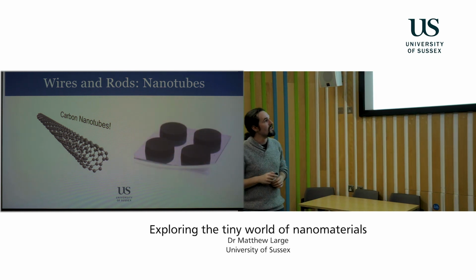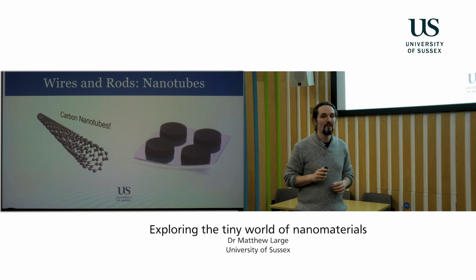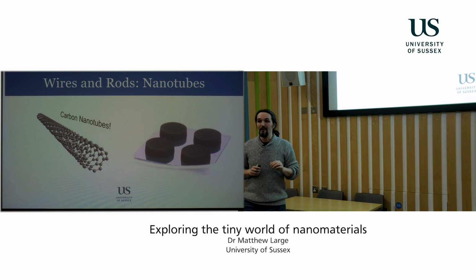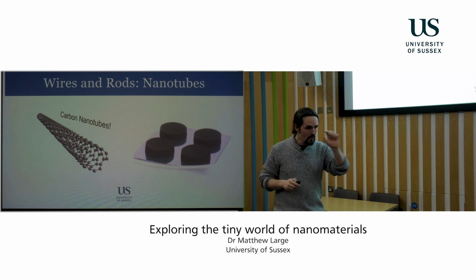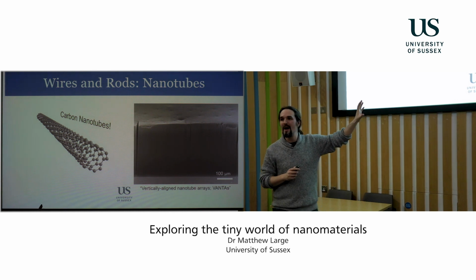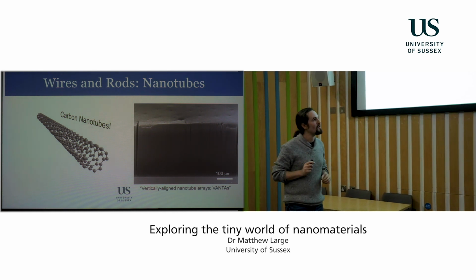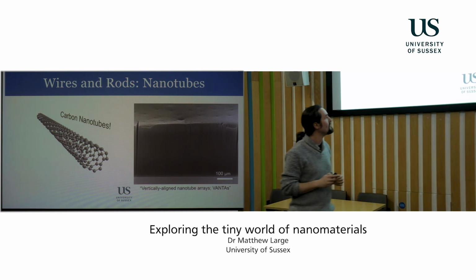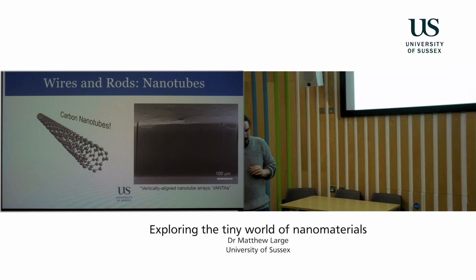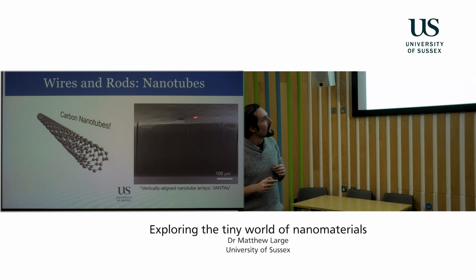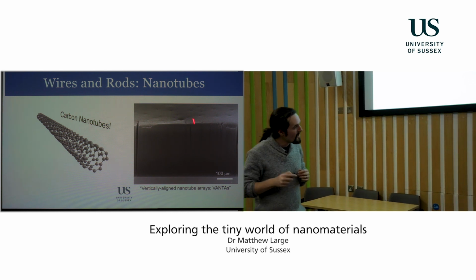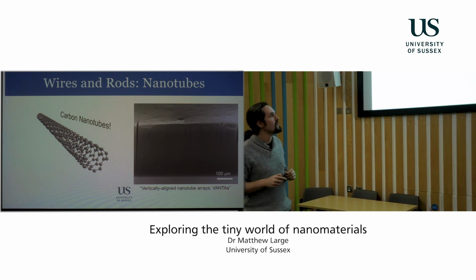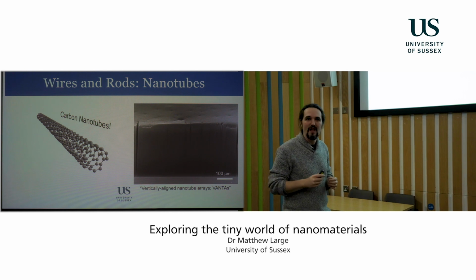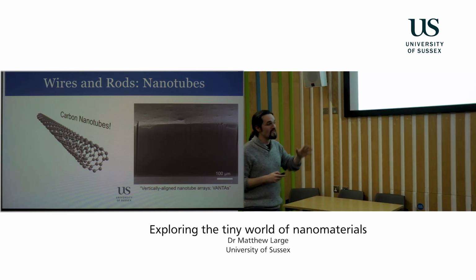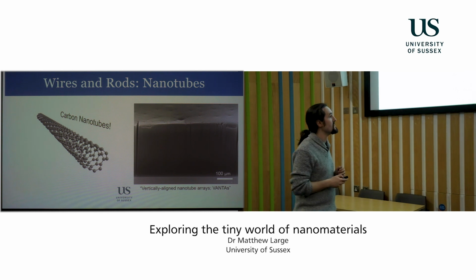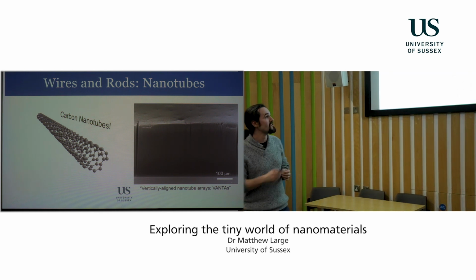What happens if you do that is you're left with these beautiful little cakes of carbon nanotubes. But the cool thing about them is if you put one of those in the electron microscope and look at that edge, what you find are these gorgeous, almost bamboo forest-like structures. Carbon nanotubes all perfectly straight and packed together vertically. Now we can do some things with these, but also they have some interesting properties of their own. Because of this structure, when they're very, very aligned in that one direction, light, when it falls on the surface, basically rattles down between these nanotubes. The nanotubes are black. So this means that these absorb almost all incident light that falls on their surface. They are the blackest material in existence.